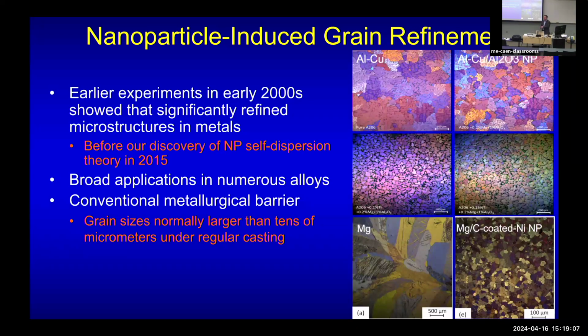We always found out one thing: we put nanoparticles in, and always get a grain refiner, right? Very good, very effective grain refinement. Of course, before 2015 we didn't have the self-dispersion theory, so our dispersion was not so good, but nonetheless the grain refinement was always good. But commercially, we couldn't get success because we couldn't get scale-up production. And at that time, nanoparticles were more expensive than conventional grain refiners. We didn't have anything really revolutionary at that time to make that happen.